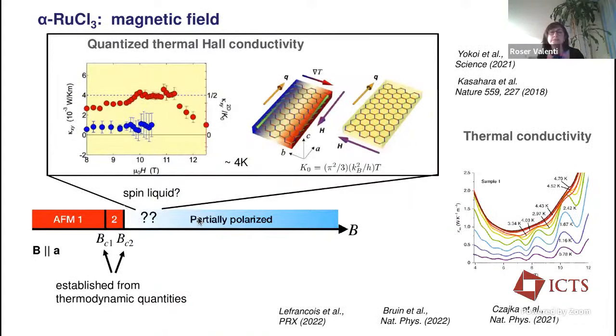But just let me show you at least what has been done up to now and why this field has boosted a lot: it was because of these measurements in the group of Yuji Matsuda in 2018 of the thermal Hall conductivity. So basically what they did is they applied a magnetic field parallel to the plane. And in fact, the direction of the magnetic field is important because of these very anisotropic spin interactions, you have of course a very anisotropic response. So if you want to suppress the zigzag order, the easy axis is the easy plane. So in the perpendicular direction, this is the hard axis of the system and you have to apply magnetic fields of 70 Tesla at least to suppress the long range order. So you should apply your magnetic field parallel to the honeycomb plane.